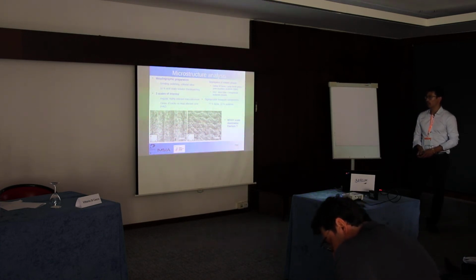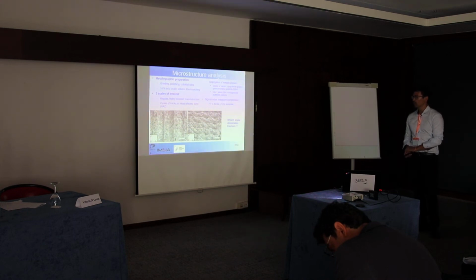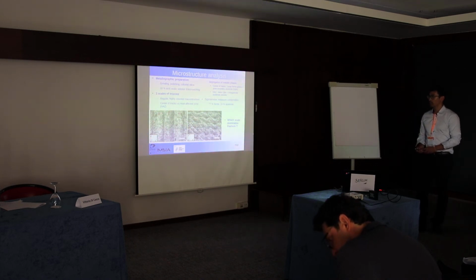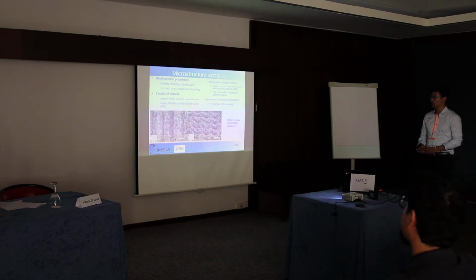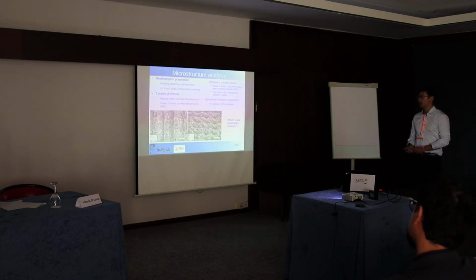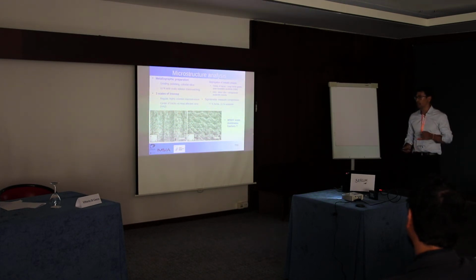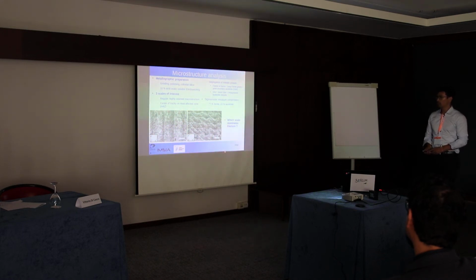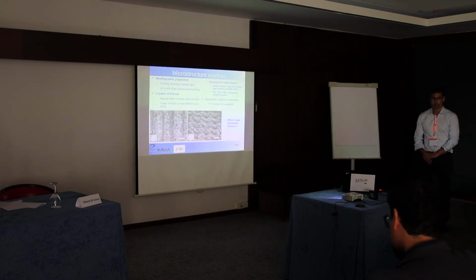First of all, there is, I wrote macrostructure, but I think mesostructure would maybe be a more correct term in this case. So the structure that is inherited by the printing direction. Next, when we zoom in on a single track, we can see a difference with large grains in the center of the tracks compared to much smaller grains in the area surrounding it. We explain this by the fact that these regions are actually heat-affected regions due to the subsequent passages of the laser.